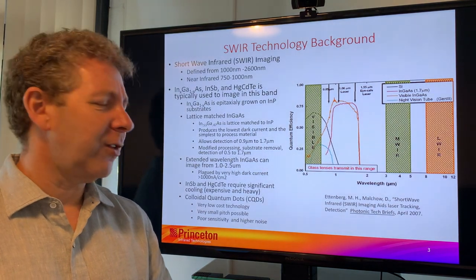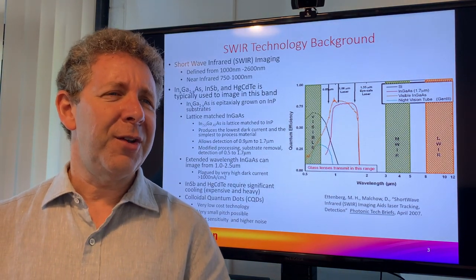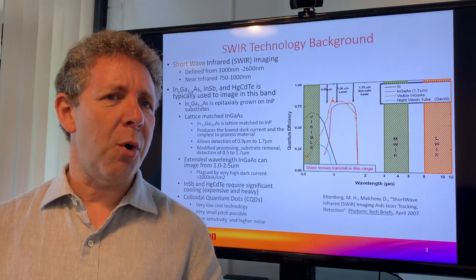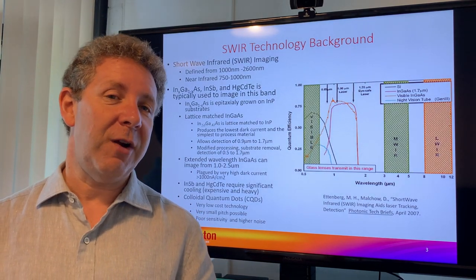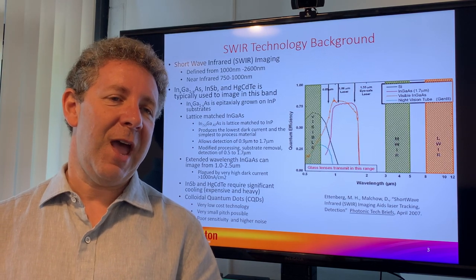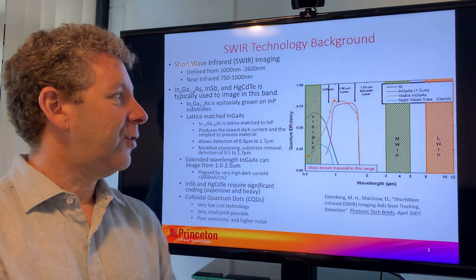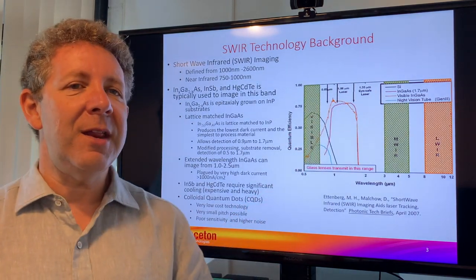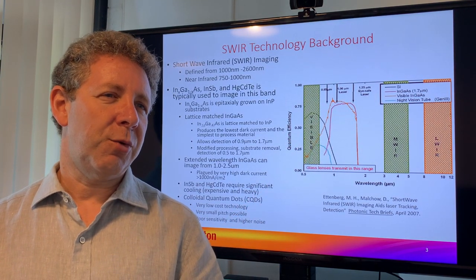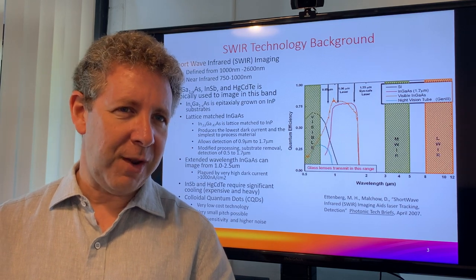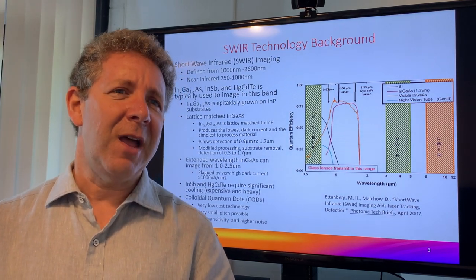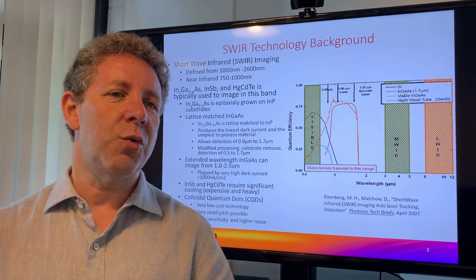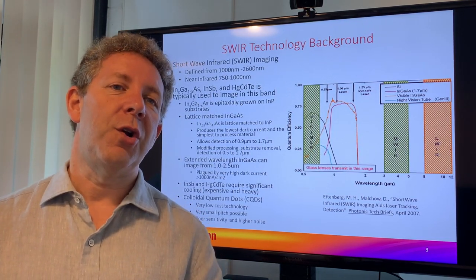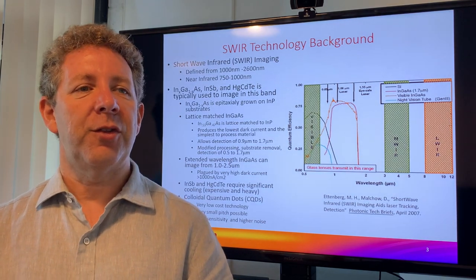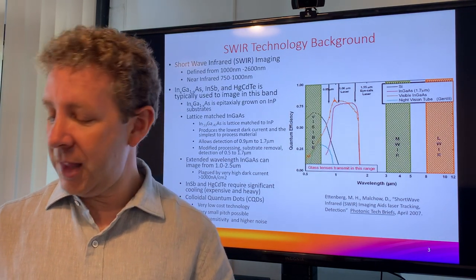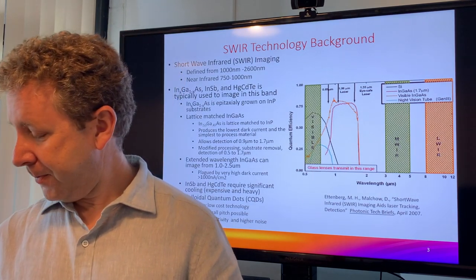The other material we're starting to see is colloidal quantum dots. They're coming onto the scene now. They can allow for smaller pitch. Their advantage is the very low cost. Their disadvantage is they have very low quantum efficiency. As you see here, quantum efficiency of InGaAs is somewhere in the 80-85% region. Colloidal quantum dots are somewhere around 5 to 10%, maybe 15 at best. And they also have about 10 to 50 times more dark current. So they're noisier, they collect fewer photons, so their overall signal to noise ratio is significantly less. But they're a lot cheaper.